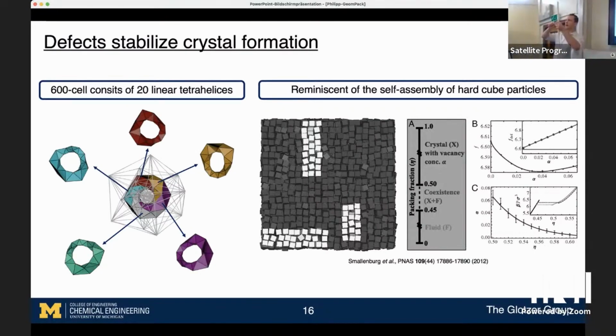It's pretty much that the particles are also very likely to switch between two sites. Which means that they're often not collectively moving all in one direction, but it's more that you have an interstitial, and therefore it's easy for them to position themselves in between two lattice sites. Exactly.